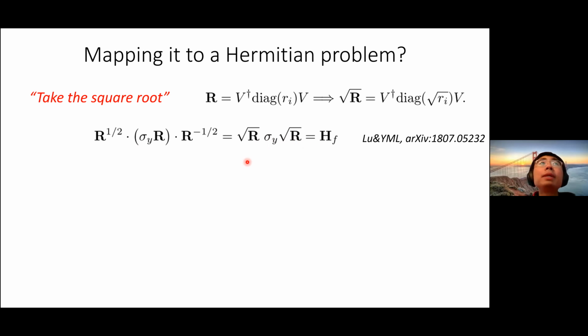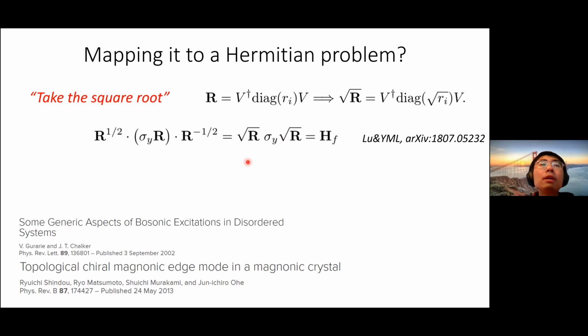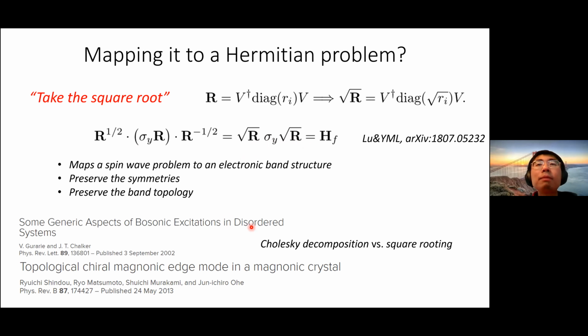This approach has been used previously in some other systems, such as disordered bosonic systems. But the trick used in those systems is slightly different from our case, in the sense that they use something known as Cholesky decomposition, whereas in our case we use a square root of this matrix.